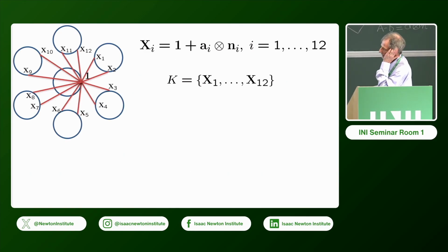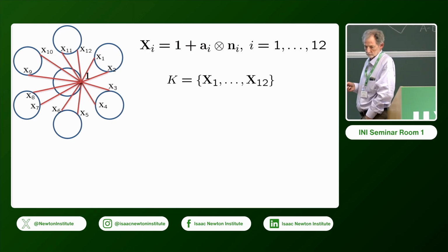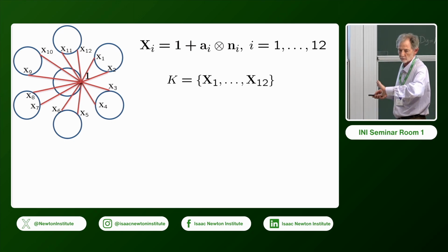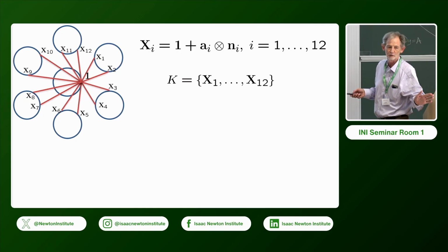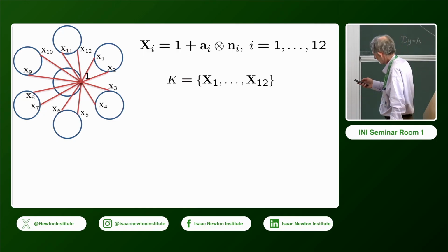So here's the picture then. Here, energy wells SO3 times something are represented by circles. Of course, they don't look like circles, but that's the way they're represented. The middle one is SO3, and of course the identity belongs to SO3. We could have taken any rotation in SO3 and you get the same picture. And now we see that there are exactly 12 matrices, 2 on each well, that are rank 1 connected to the identity.